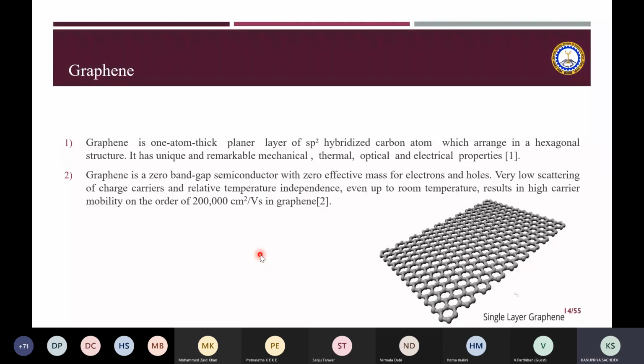Now we move on to another allotrope, which is graphene. And as we just discussed, it's a one atom thick planar layer of sp2 hybridized carbon atoms arranged in a hexagonal structure. And it has very unique and remarkable mechanical, thermal, optical, electrical properties. I showed you the band structure earlier, and that shows that the two Dirac cones meet at a point and there is no band gap there. So effectively, it's a zero band gap semiconductor with zero effective mass and very low scattering of charge carriers. And relative temperature independence results in a very high carrier mobility. Theoretically, it is of the order of 2 times 10 to the power 5 centimeter square per volt second, and that makes these electrons ballistic.